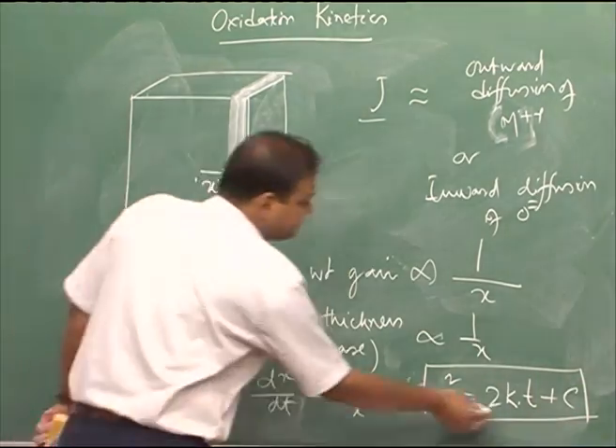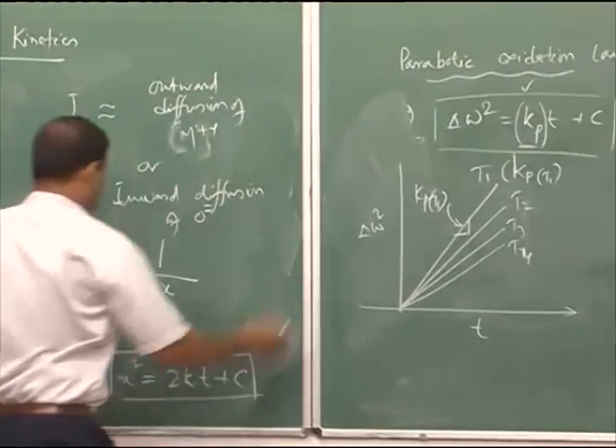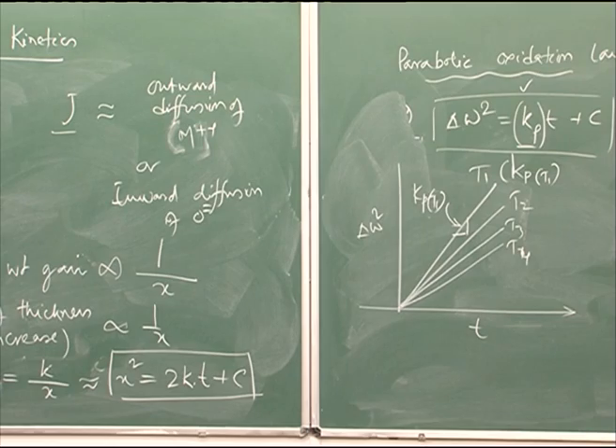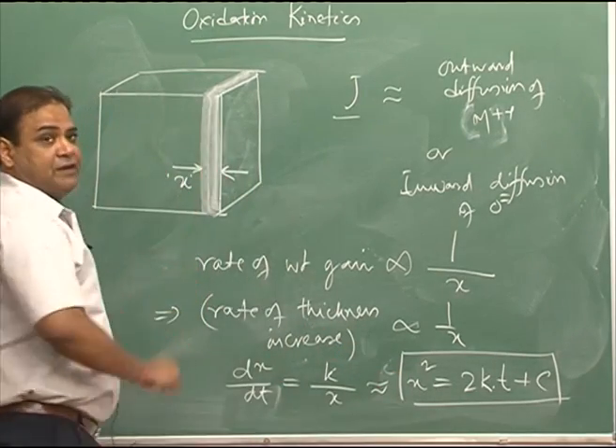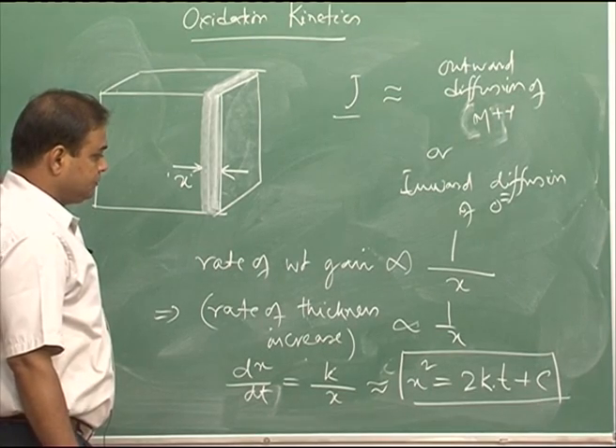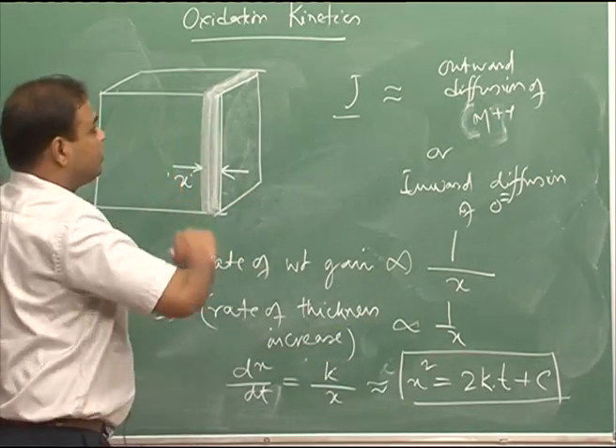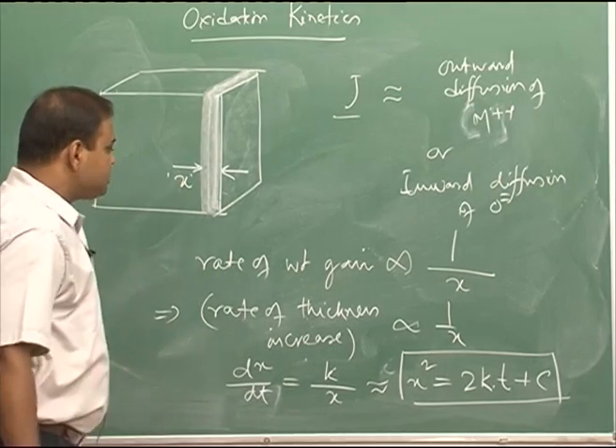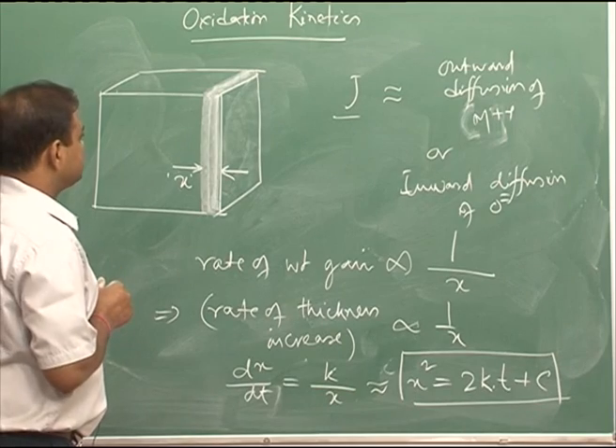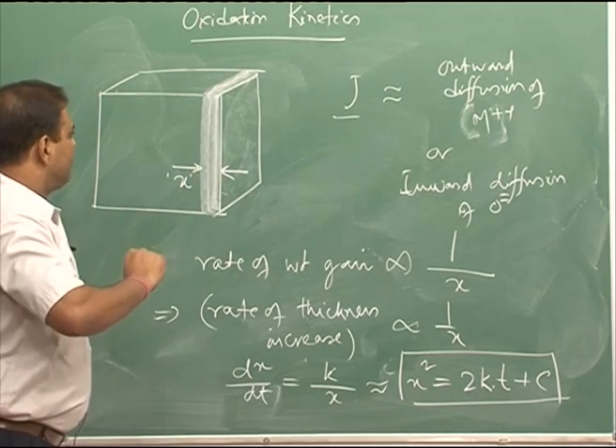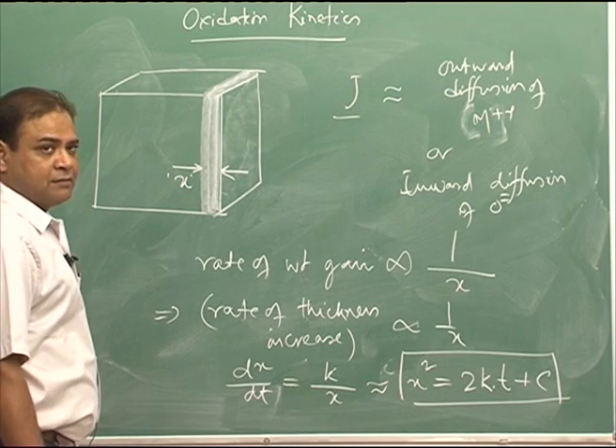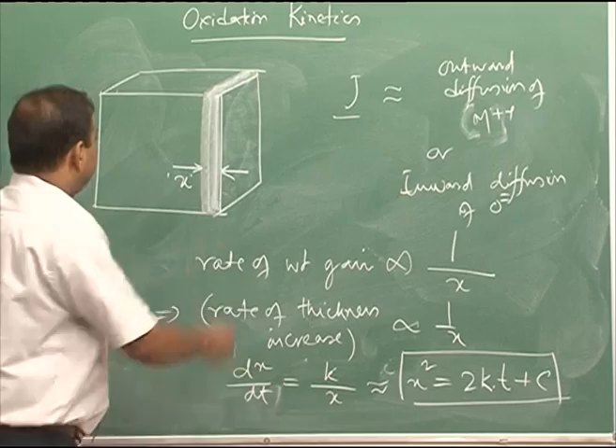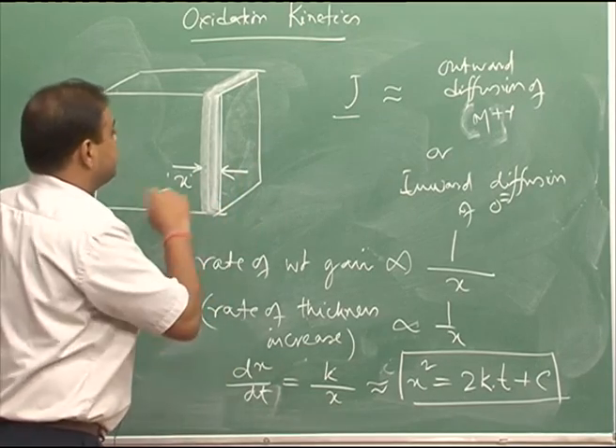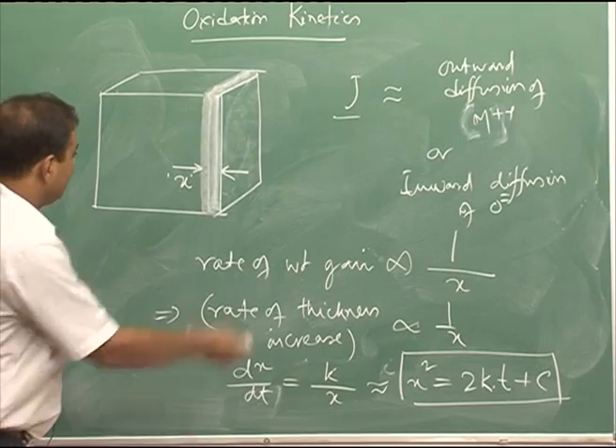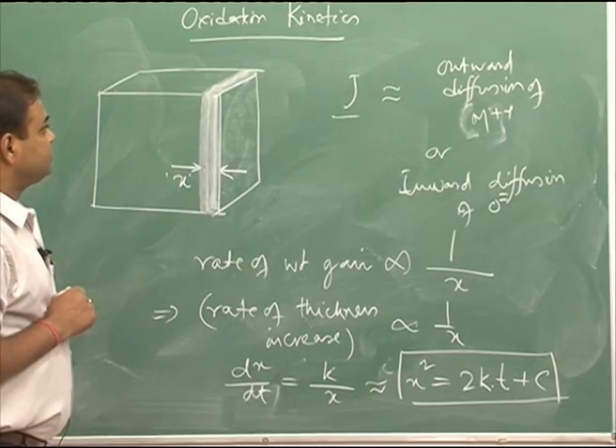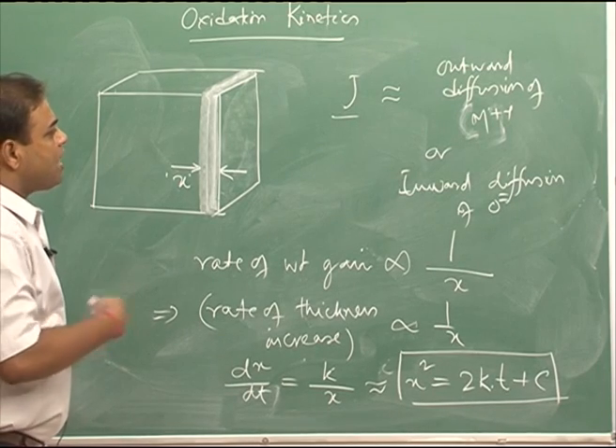So, that means we see that it is almost similar form like this, where del W is actually proportional to the thickness of the oxide layer. So, this parabolic oxidation can be proved through this simplistic approach, and there are many assumptions here. One assumption is that the mass flow rate is steady state. That means the steady state diffusion of either metal ion or oxygen ion is taking place through the oxide layer.